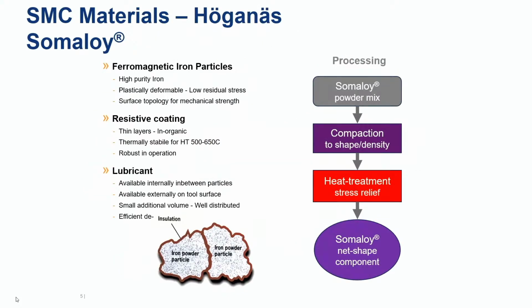And just a few simple words about soft magnetic materials. We start from a high-purity iron powder, and we use a surface insulation, very thin. This insulation is around 10 to 100 nanometers. And then you mix with a lubricant. This is almost the same as the normal powder methodology. Then you compact the powder into the component, then heat up the component to a certain temperature for stress releasing. Then you can get a component with a 3D shape. So I should also mention 3D motor topology. It will be very important for new applications.